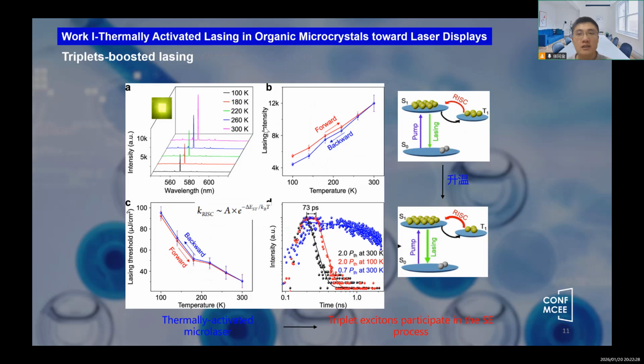A unique thermally activated lasing phenomenon was observed during variable temperature laser characterization, where the laser intensity gradually increased with the increasing temperature. This experimentally demonstrates that triplet excitons in the system can be captured and used for singlet stimulated emission, achieving high-performance laser output.